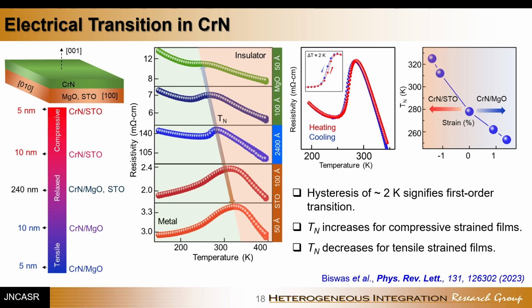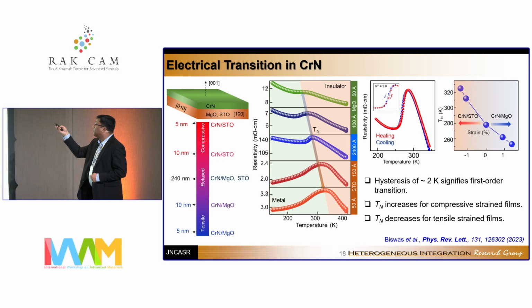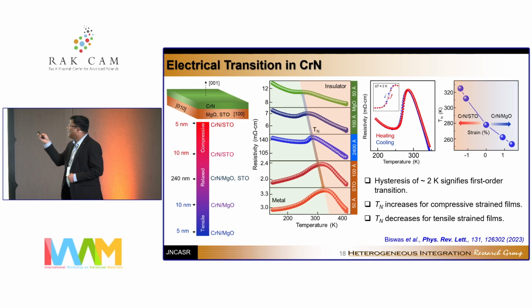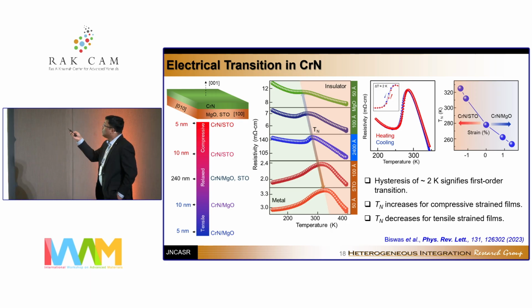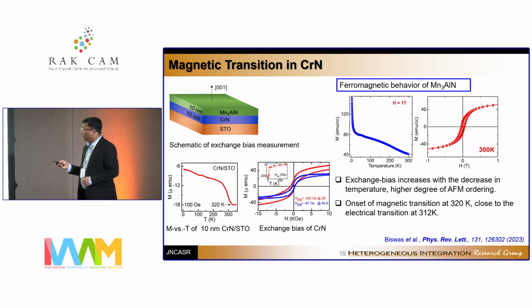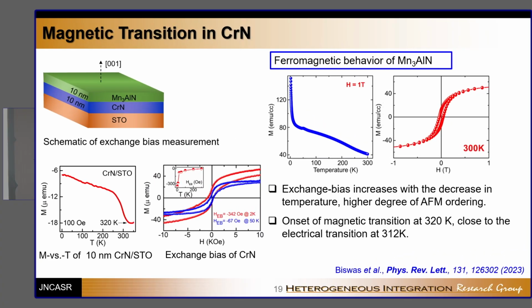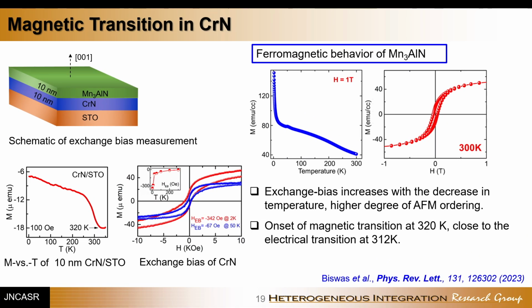In the compressive strain, because the atoms are coming close to each other, your exchange energy basically increases, and that really pushes up the Néel temperature. On the other hand, the tensile strain on MgO basically reduces the exchange coupling, so that reduces the MIT transition temperature. Along with that, we did magnetic measurements also to verify that the shift in the MIT temperature is actually seen in magnetic measurement. And this is the 10 nanometer chromium nitride film on STO, which showed the metal insulator transition moved from 270 Kelvin to around 320 Kelvin.